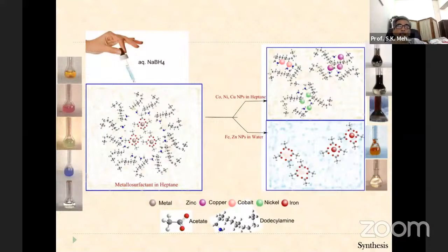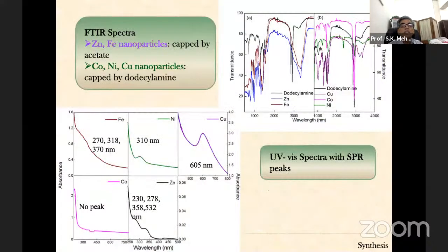So the metallosurfactant is in heptane. You are using sodium borohydride. We have prepared copper, nickel, and cobalt nanoparticles, which you can see in n-heptane, whereas iron and zinc are in water. So this bi-phasic solution is there. You can see easily the color change will tell you the nanoparticles have been formed, and you can separate them because it's a bi-phasic system.